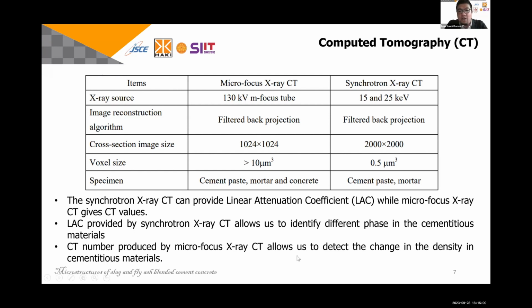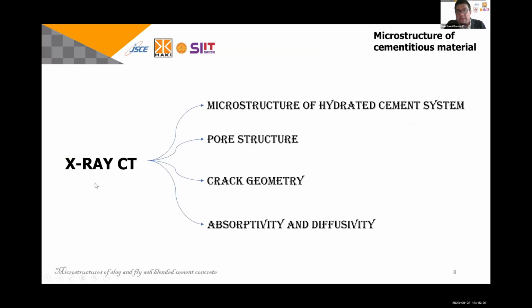And then the CT number produced by microfocus X-ray CT allows us to detect changes in the density of the cementitious material. So by using microfocus X-ray CT, we could find the difference, for example, before and after leaching test, before and after carbonation test, and before and after high temperature exposure. Here, I try to explore the use of X-ray CT in four topics: first, microstructure itself, and then pore structure, crack geometry, absorptivity, and diffusivity.